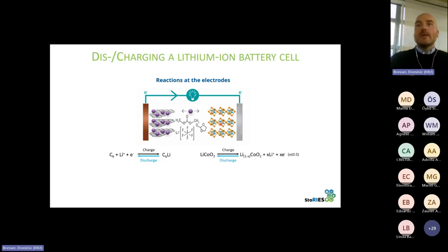And at the positive electrode, let's take lithium cobalt oxide as an example for simplicity. Upon charge, we're de-intercalating lithium cations from the structure, and upon discharge, basically the reverse. In lithium cobalt oxide, we can do this with about 50% of the lithium in the structure. Before then, at some point, the structure tends to collapse. In fact, it tends to collapse because it's a kind of layered structure, just like graphite, which is a bit difficult to see from the scheme.